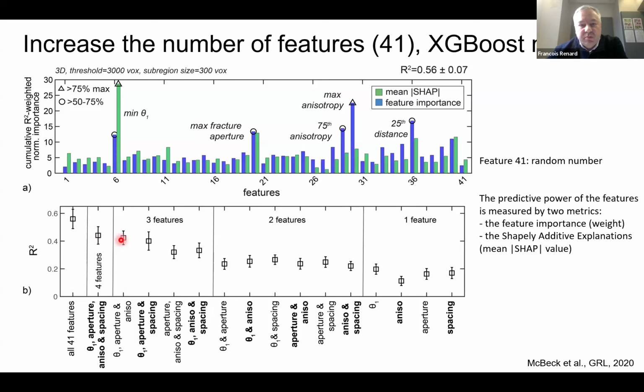We can also use the 3 best features, only 2 features, only 1 feature. When we have only 1 feature, then the R2 starts to decrease below 0.2, so the correlation between the prediction and the true distance to failure becomes very weak.